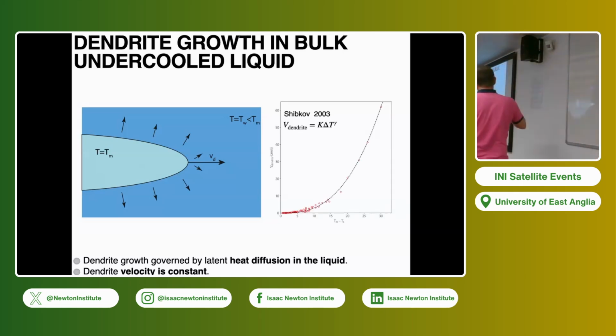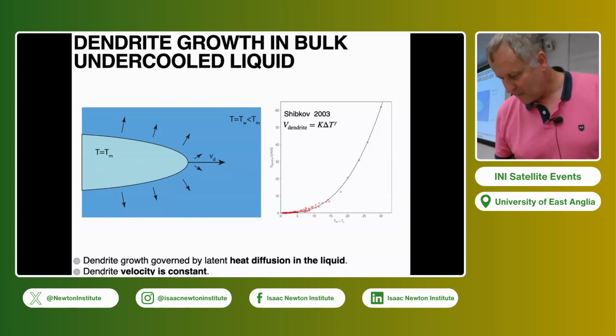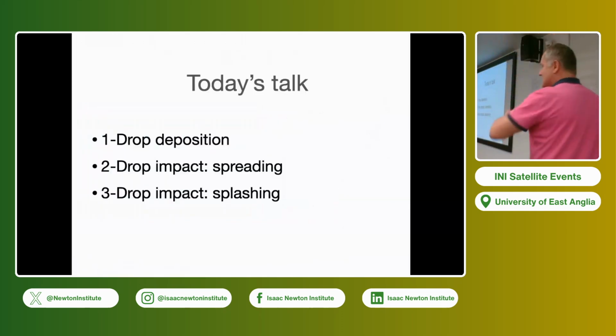And if you compare the theory with the numerics and with the experiment, in the experiment you have this relation between the velocity of the dendrite as a function of the undercooling, so the melting temperature minus the temperature of the water. The theory can account for what happens here, but in experiments you have this nice experimental shape, and it can be fitted by a velocity of the dendrite that goes like k times delta T to the power gamma, with some fitting value for gamma. Okay, so today, after this